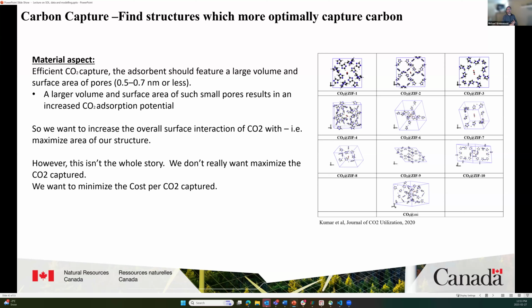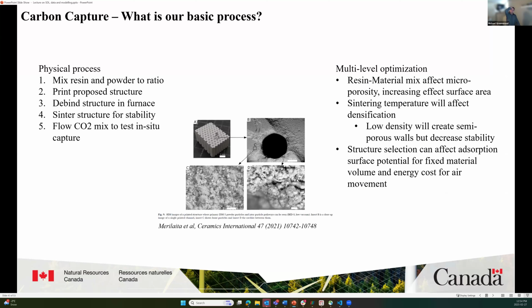And then there's the complexity of the print, which can impact your pressure gradient across your cell, which will result in an overall increase in energy cost. So if you printed a very dense open cell foam where you had a ridiculous surface area, but you had to push the air ridiculously hard such that you have a huge pressure gradient across your cell just to move the air through it, then you might have more surface area and capture more CO2 per cycle, but it may have cost you more energy. So it becomes a trade-off there.